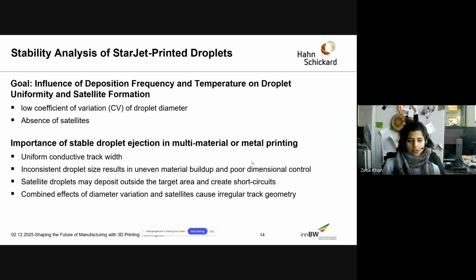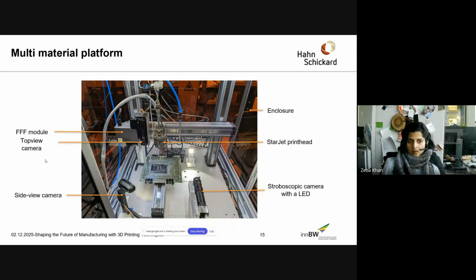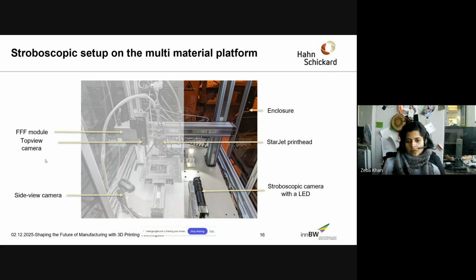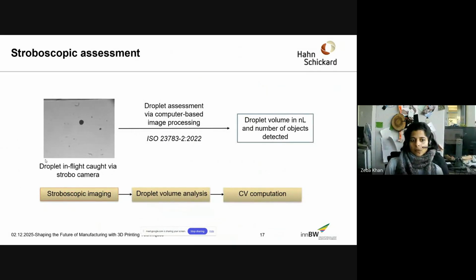In order to ensure this sustainable manufacturing, we make sure that the droplets that we have to print from the StarJet, where each droplet must be printed to have continuity in the conductive tracks, go through a thorough stability analysis. In this case, we use the same multi-material printing platform, only focusing on the stroboscopic setup part of the platform. In this stroboscopic setup, I'll give you a quick overview of how we do it.